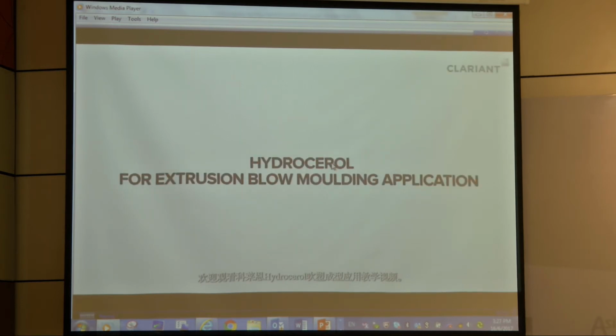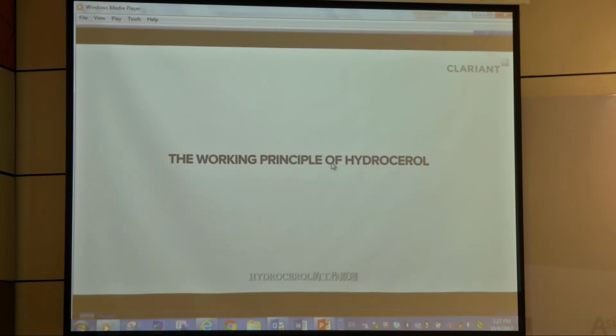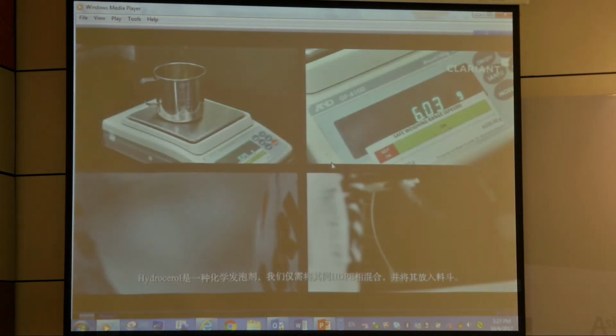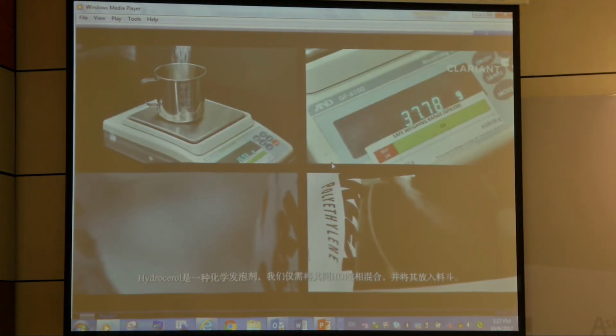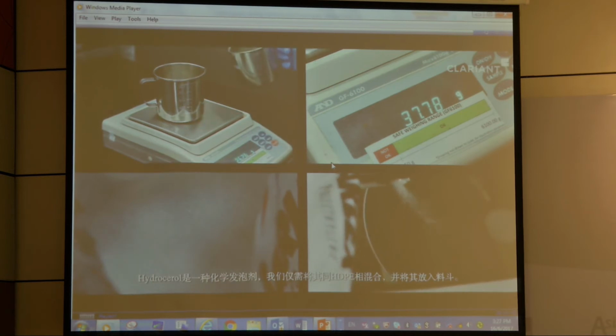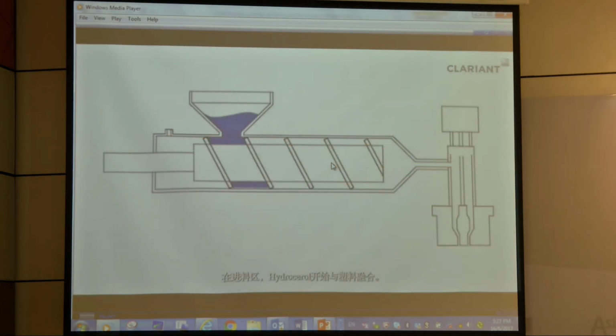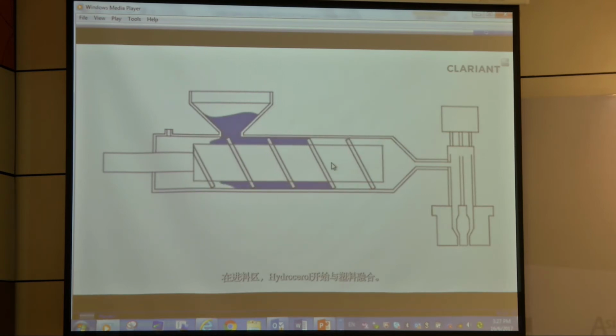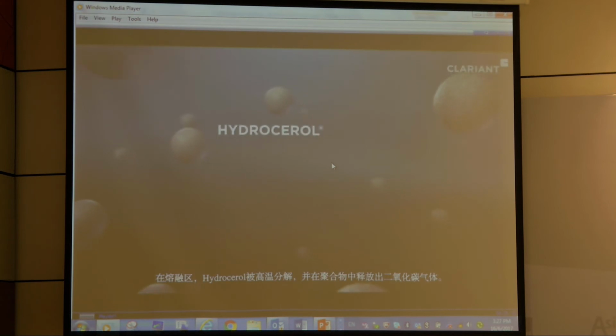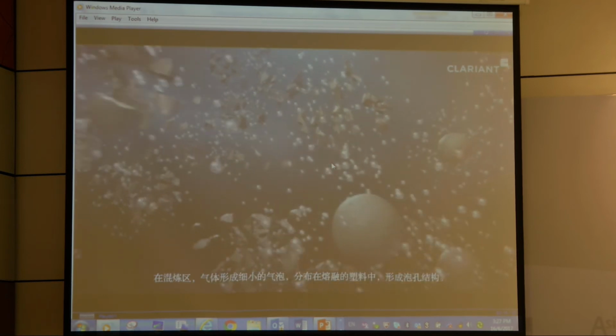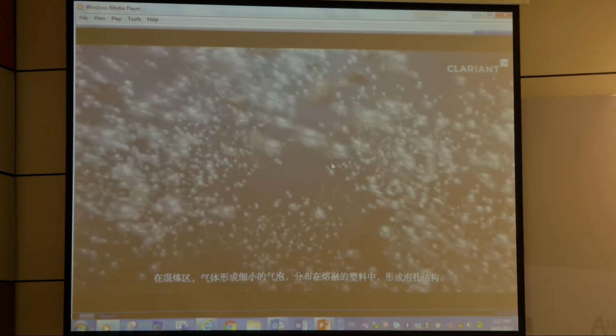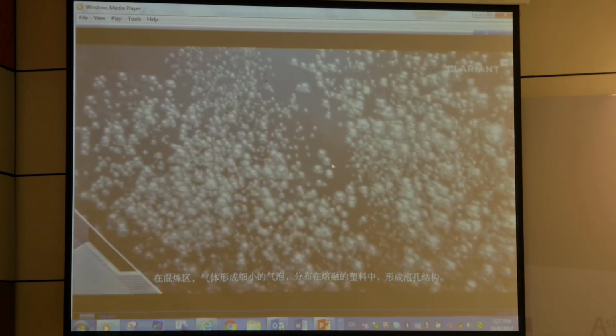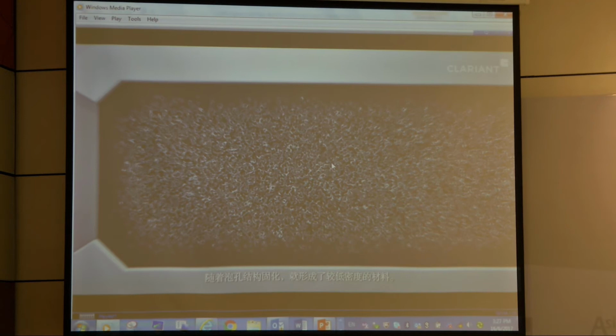Welcome to Clariant's Hydrocerol for Extrusion Blow Molding Application Tutorial Video. The working principle of Hydrocerol. As Hydrocerol is a chemical foaming agent, you simply need to mix it with HDPE resin and put it into the hopper. At the feeding zone, Hydrocerol starts melting into the plastic. At the melting zone, the Hydrocerol decomposes under heat and releases CO2 gas in the polymer. At the mixing zone, gas forms into fine-sized bubbles and distributes itself into the plastic melt to form a cell structure. When the cell structure becomes solid, you will have less dense material.